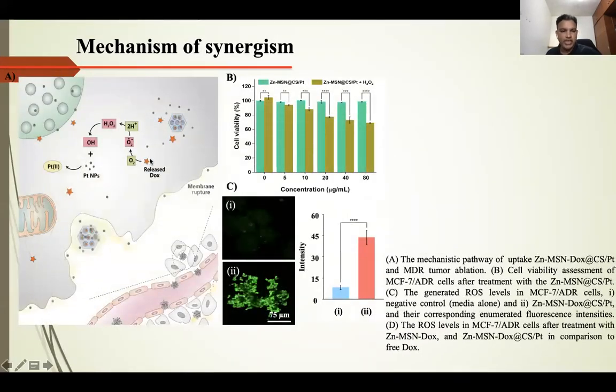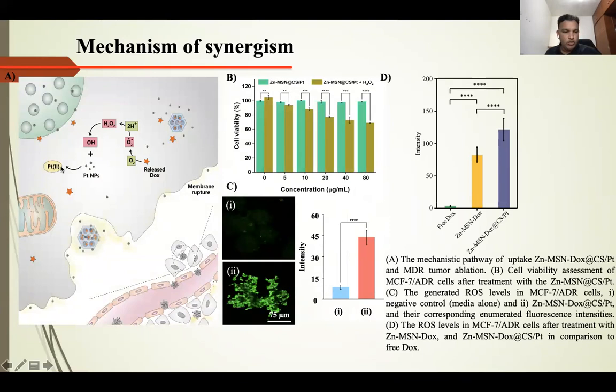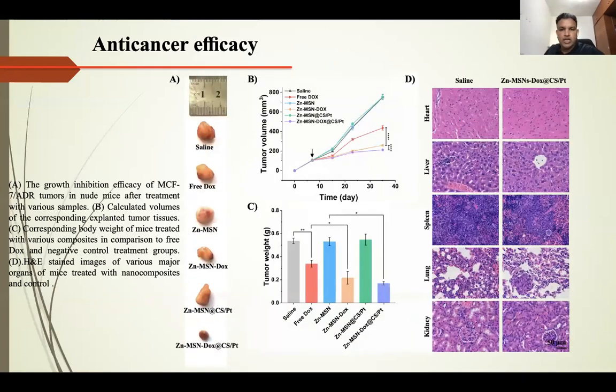So the mechanism and synergism acted like this. Not only the deep penetration, but also the Pt nanoparticles after entry created Pt ions, which are also toxic to the cancer cells. The cell viability slightly reduced, whereas the ROS levels were also pretty high. And with the combination of this, the ROS levels are significantly high enough to kill the cancer cells. And further, we did animal experiments, where you can see the final formulation significantly reduced the tumor growth.